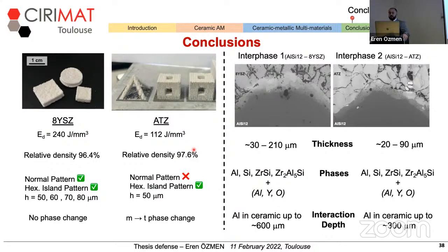For the multimaterial side, we see that the first interface is thicker than the second one, and that was also identified in microprobe analysis. And very similar phases appear in both interfaces, even though the joined multimaterials are quite different from each other. And the appearance of the amorphous phase among aluminum, yttrium, and oxygen was observed for both interfaces as well. And the interaction depth is larger than, as we explained,